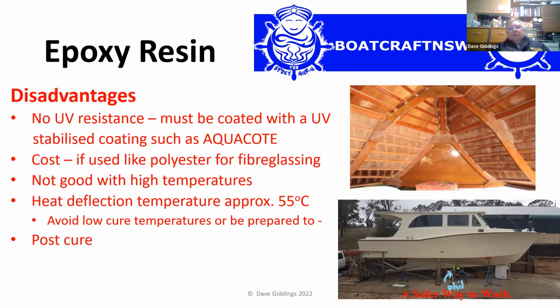The disadvantage with epoxies is they've got no UV resistance. And a good example is a concrete swimming pool that's been painted out with epoxy. If it's been there for a while, it'll be nice and bright below the waterline. Above the waterline, it'll be all chalky. That's the UV getting to it. UV breaks down the molecular structure of epoxy if you leave it to it. Fine, as soon as you put a coating over it, you know, and polyurethanes stick very well to epoxy.